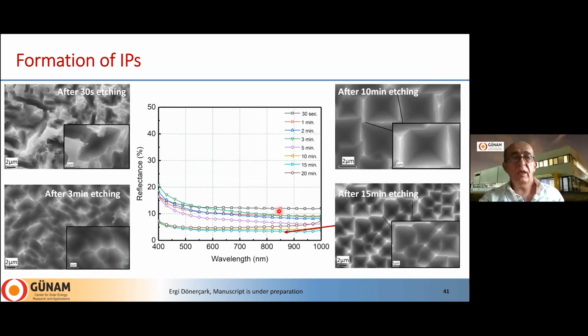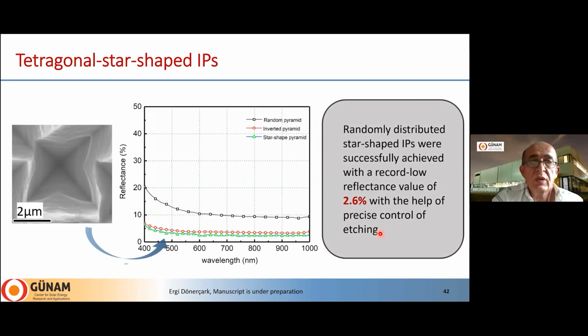But in our center, we developed a technology which is based on copper-assisted etching. This is a metal assisted etching, actually. And here we form these inverted pyramids on the surface by using a chemical rather than a lithographic process. So there is no lithography here, and we can reach extremely good surface structures by using this copper-assisted etching. Here, this is our record.